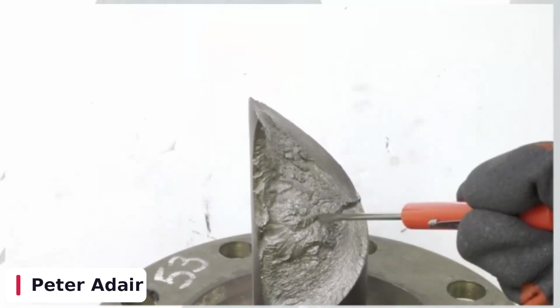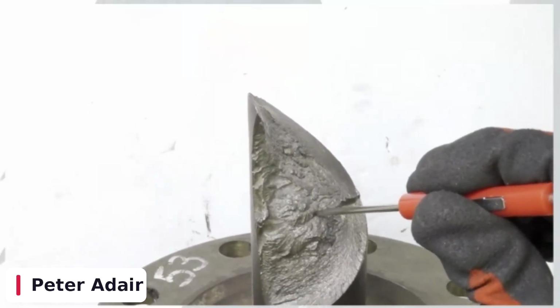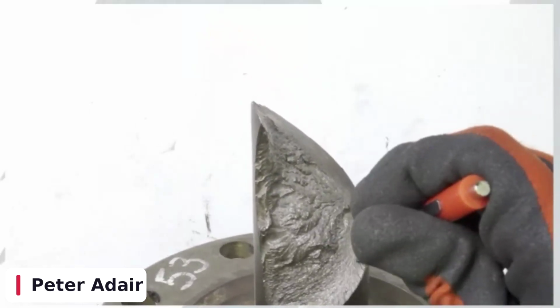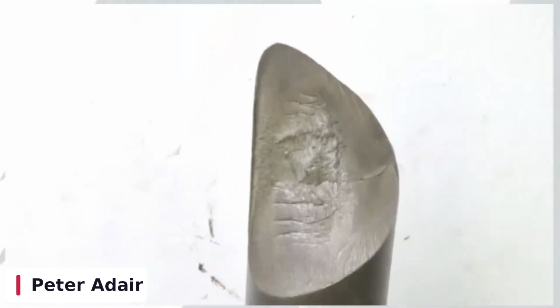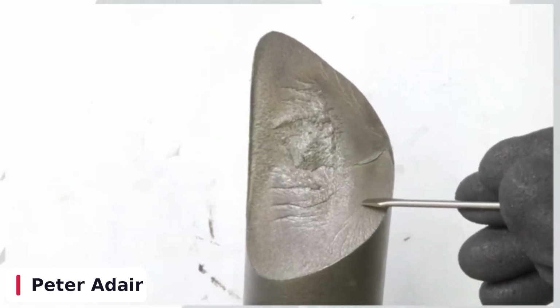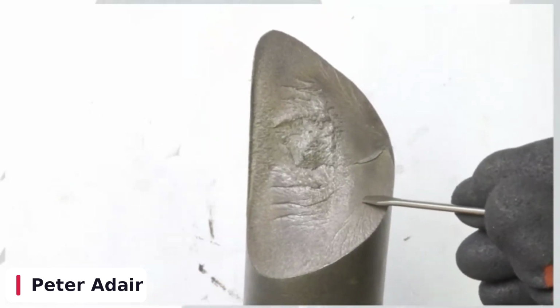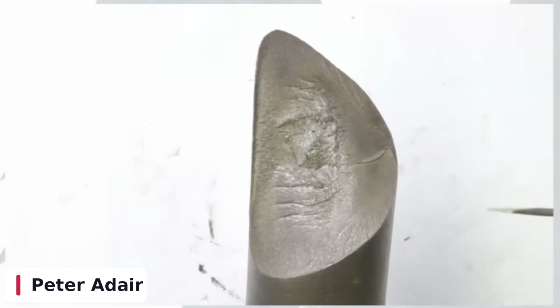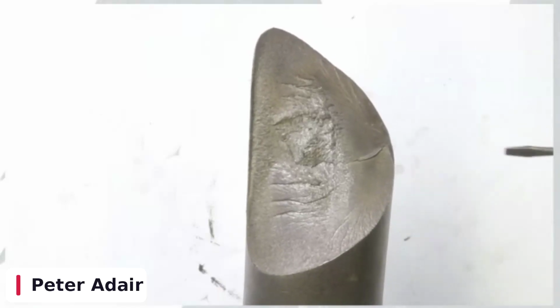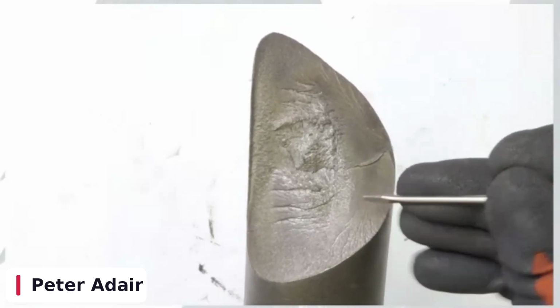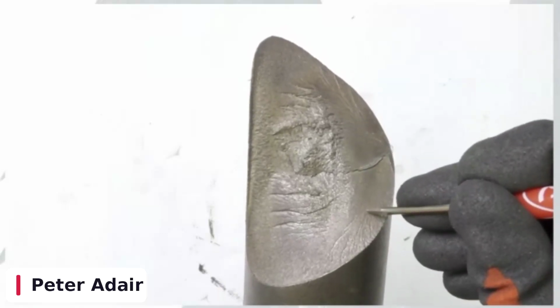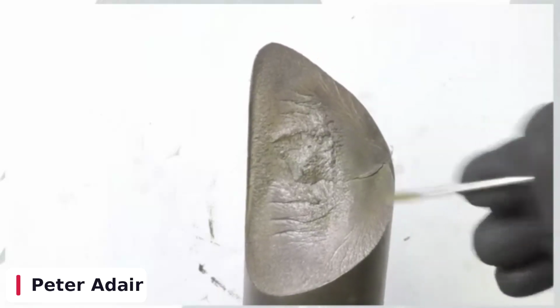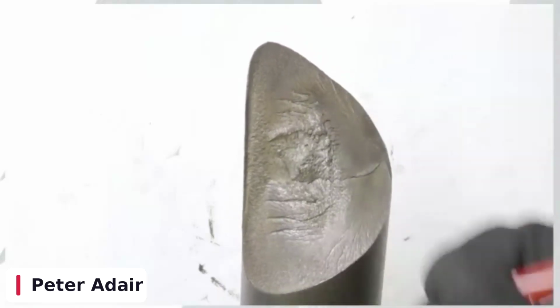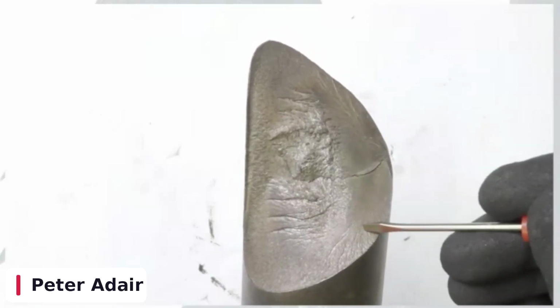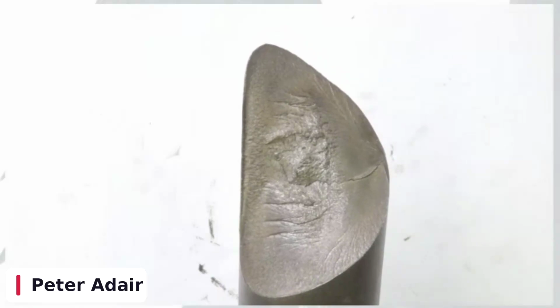The soft core is what allows this shaft to bend or rotate 360 degrees in return. And then the hardened steel shell is what brings it kind of back to shape. So that hardened steel shell makes the part work where it's supposed to work in terms of the foot-pounds of torque, the weight ratings, everything that the commercial truck's seeing, 80,000 pounds, 15,000 foot-pounds of torque, everything is going to come through this hardened shell. So soft core, hardened shell tells me the part was heat treated. So I'm not going to think that there was something bad here that caused this part to break because I can see the grain structure.